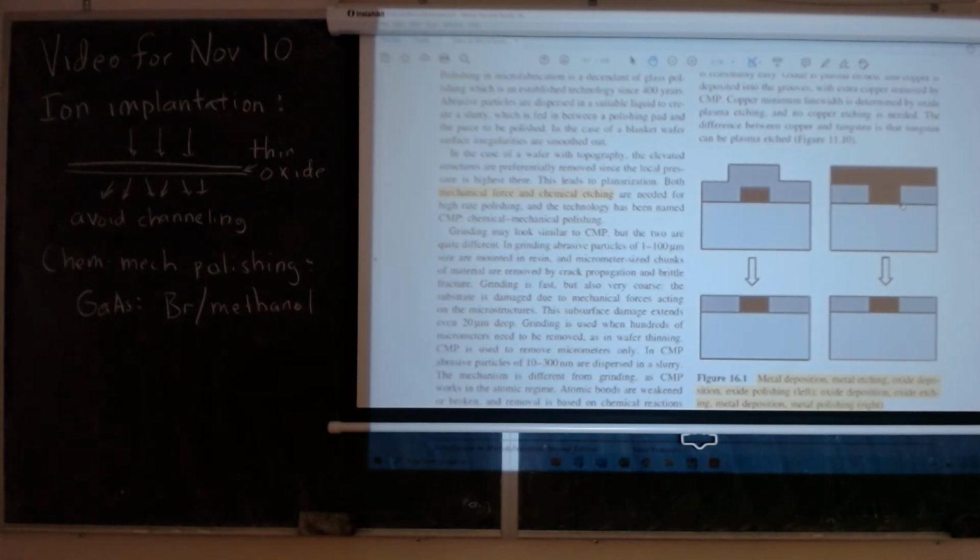And it's really astonishing that over a 12-inch wafer, they can achieve polishing and planarization down to essentially the order of a 10 nanometer level, and do this dozens of times to get an integrated circuit on a chip. I can tell you that this polishing aspect of integrated circuit chips is one of the major accomplishments of the last 30 years.